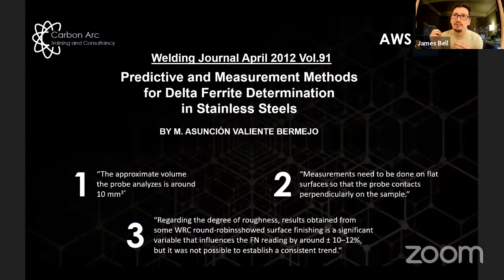So if you have a polished tube, say an incoming goods tube, and you test it, you'll get one result. If you weld it and the surface becomes tarnished or oxidized, and you test it again, you get a different result on the same component. Even if you take some Scotch-Brite or some emery cloth, scratch the surface, you get a different result.